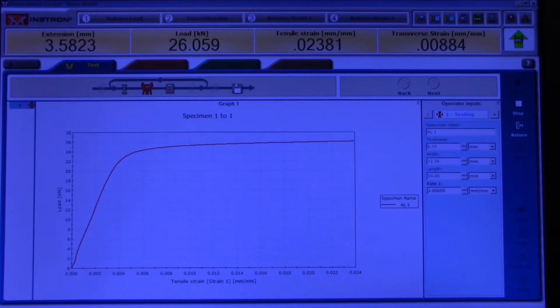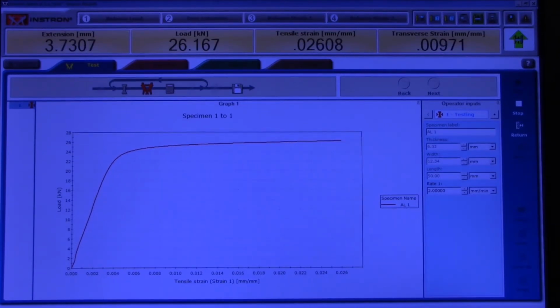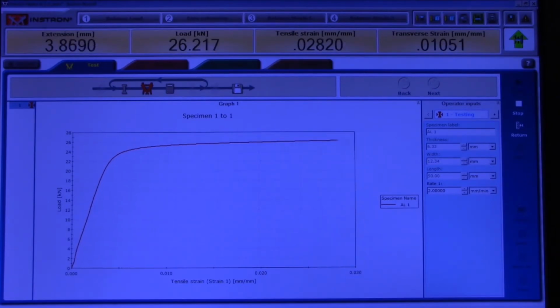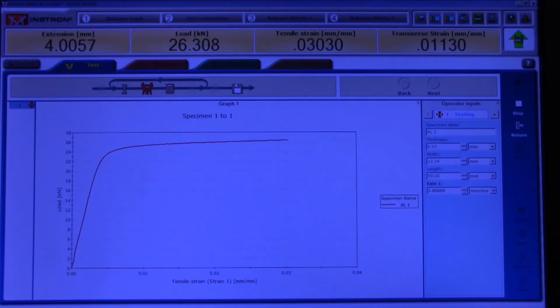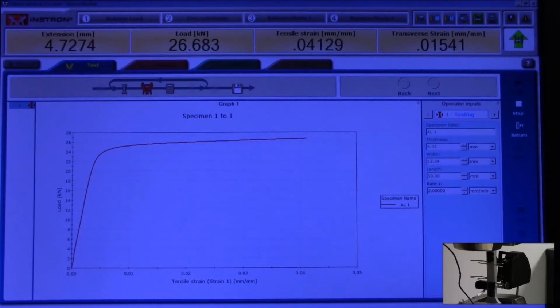Our load is still slowly increasing. And until it starts dropping, we won't really see anything happening on the specimen. Once it starts dropping considerably, we should be able to observe necking behavior, which is a narrowing, hopefully, in the gauge section. See, our load is still slowly increasing, starting to level off.